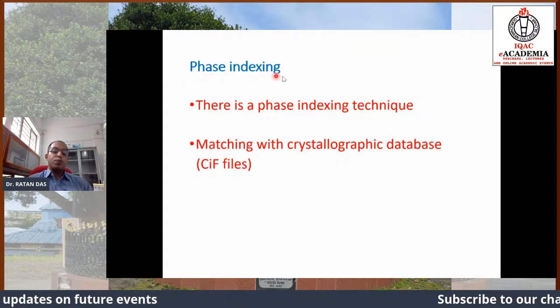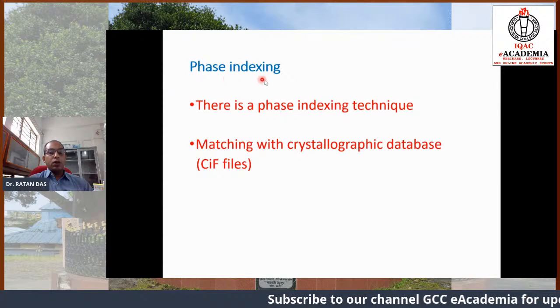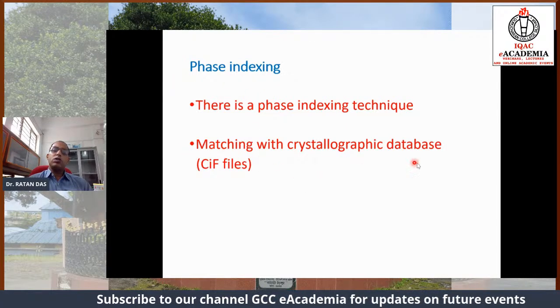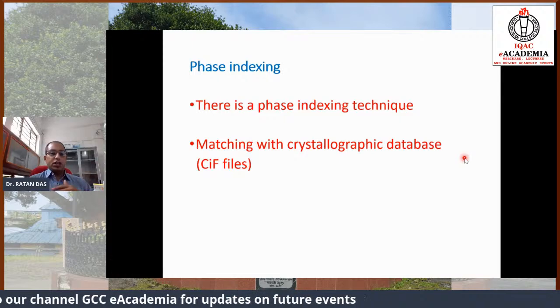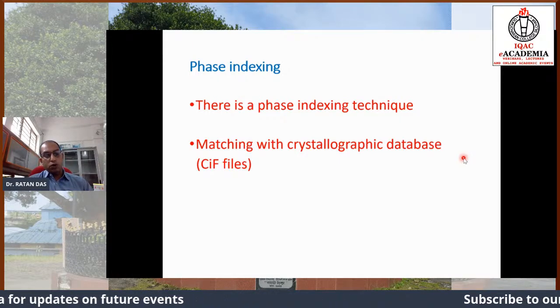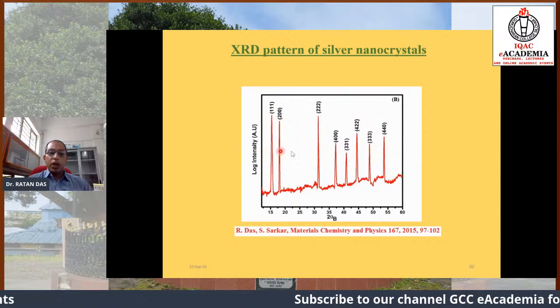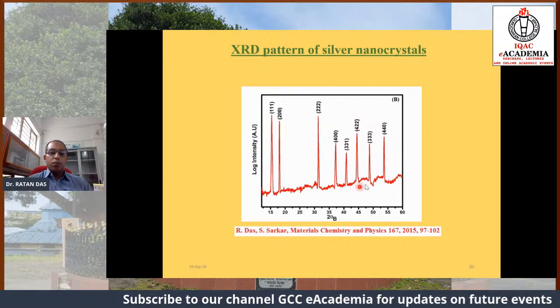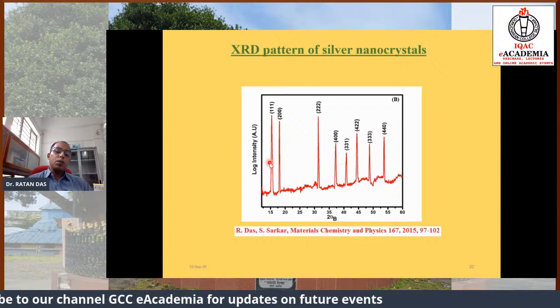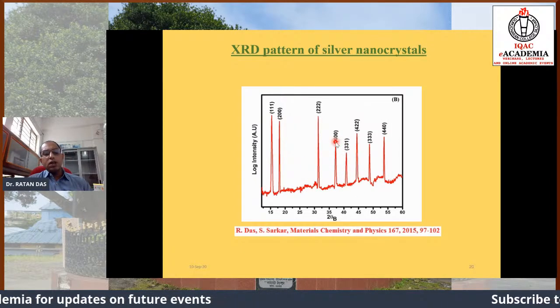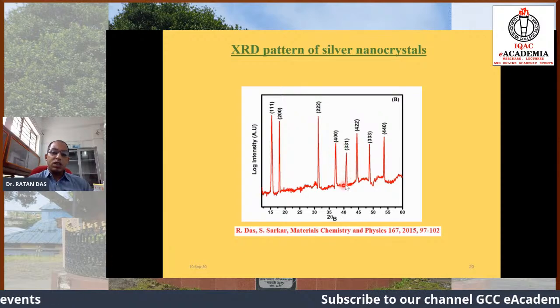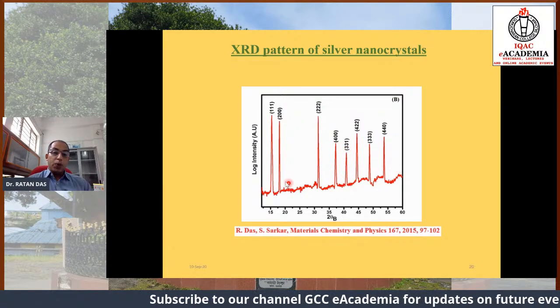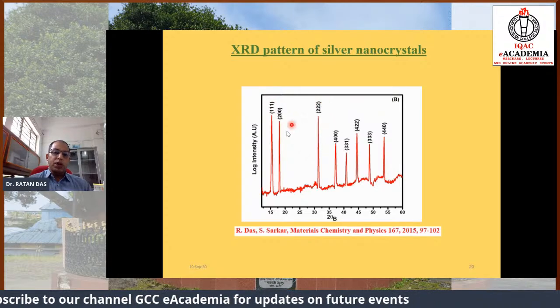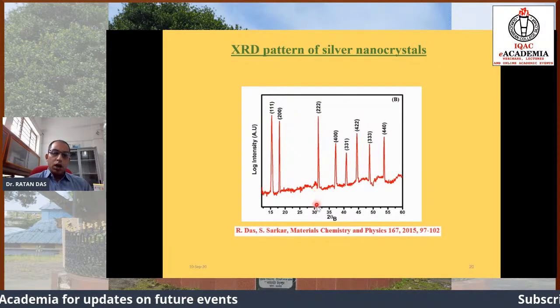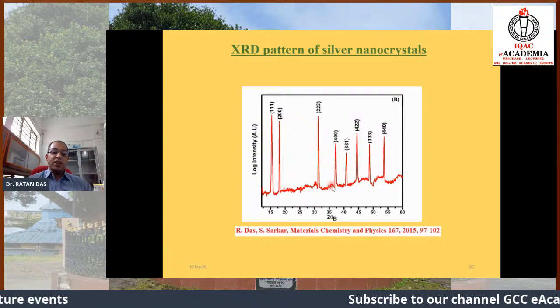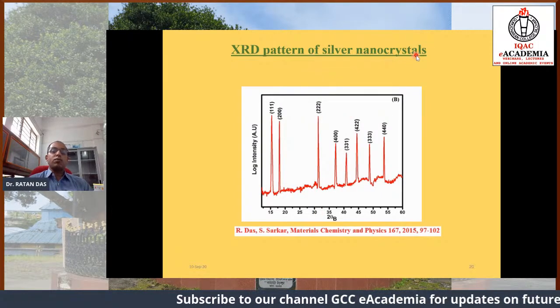nature. Suppose I have prepared silver nanocrystals, and for a particular silver nanocrystal, the pattern is fixed. Suppose what I want to say to you is that here I have obtained many diffraction patterns in the case of our silver. But if you prepare silver nanocrystals, you will find that some of the peaks may be missing, but the major peaks, suppose 1 peak, 2 peaks, will be available at a particular angle.